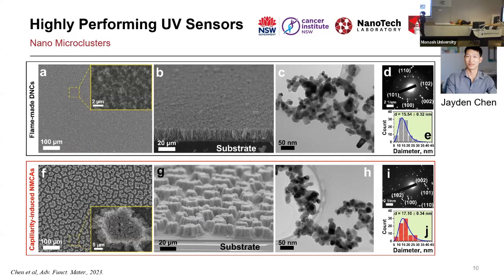Why? Because in order to do this TEM, we collect the particles from the flame-made sample, and then we dip it in the liquid, which is ethanol again. So to me, that was not really a way to see whether they are connected or not. What we did, we held the TEM grid directly above the flame. So we deposited the particles directly on the TEM grid without any influence from the sample preparation, which has the ethanol involved. The particles are completely separated.